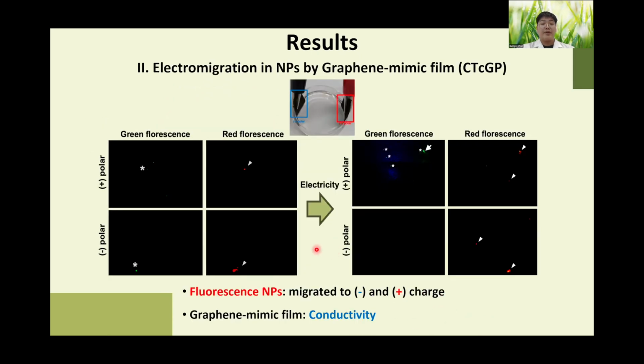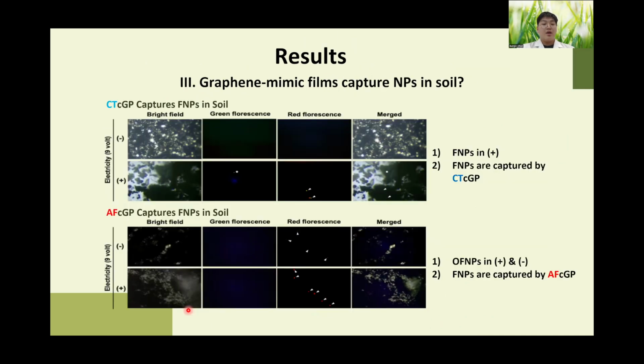Second, I confirmed whether the graphene mimicking film has electrical conductivity and whether the fluorescent nanoplastics have been charged. The results show the fluorescent nanoplastics were detected on the surface of the graphene mimicking film. Third, I determined whether the nanoplastics in the soil could be captured by the graphene mimicking film supplied with electricity.